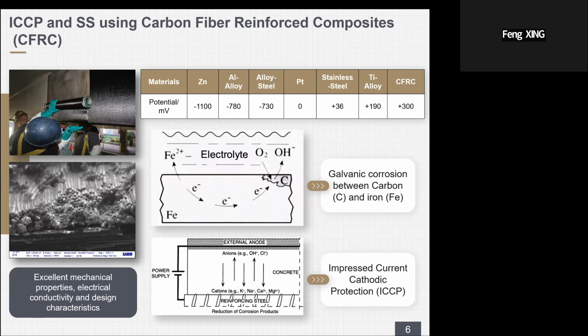Then, how about carbon fiber composites, such as CFRP? This material has been well investigated and applied in structural strengthening. Since CF is conductive, the idea came out that CF composite may be used as anode material at the same time. However, the potential of CF is much higher than steel. It means galvanic corrosion occurs when the two are in direct contact, where steel is sacrificed. This is totally opposite to the aluminum alloy case. Therefore, another electrochemical solution, impressed current cathodic protection, called ICCP, may be used.